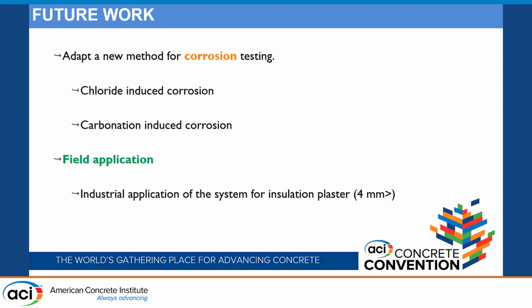Lastly, in future work, I should adapt a new method for the corrosion testing because I will submit my master thesis. So I will try the corrosion for both chloride-induced corrosion and carbonation-induced corrosion. For chloride-induced corrosion, I will find a new methodology. For carbonation-induced corrosion, I will use an accelerated carbonation chamber. And moreover, we will apply this self-healing mechanism in situ. We will apply this self-healing mechanism for insulation plaster with a width of less than 4 millimeters.